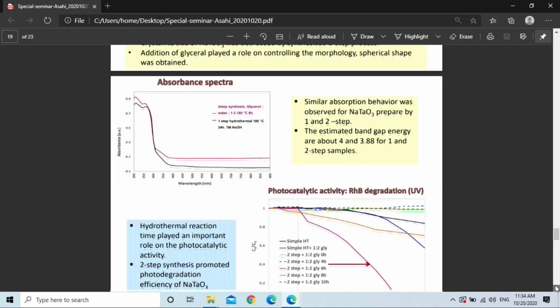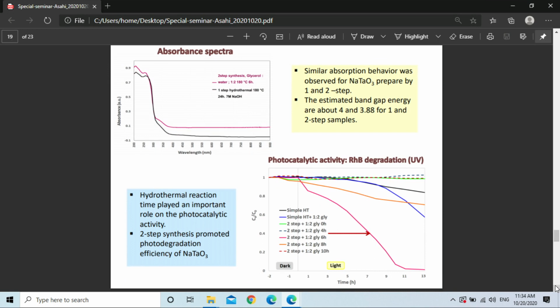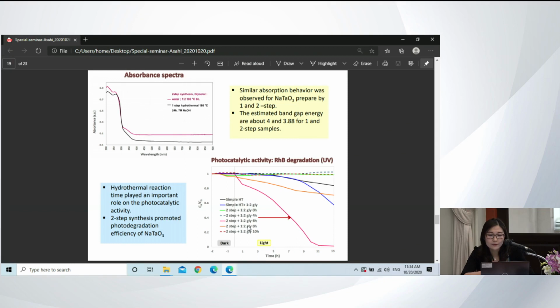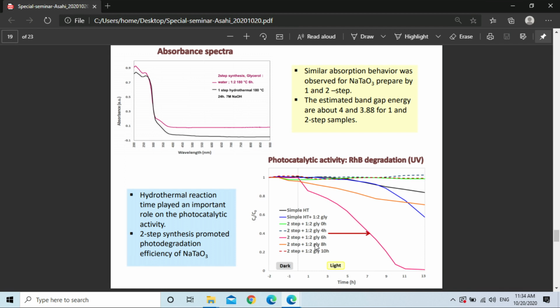And then the sample was tested for rhodamine B degradation. Because this is an undoped material, we tested under UV irradiation, and we found that the best condition for degradation comes from the sample using a 1:2 ratio of glycerol and water and hydrothermal treatment at 6 hours. So this means the time for synthesis is also very important to get the morphology and size, and also has an effect on the photocatalytic activity.